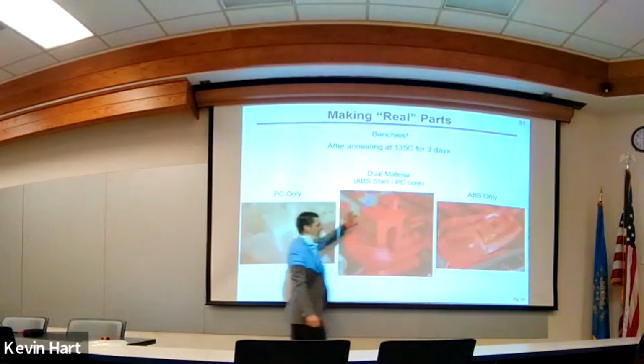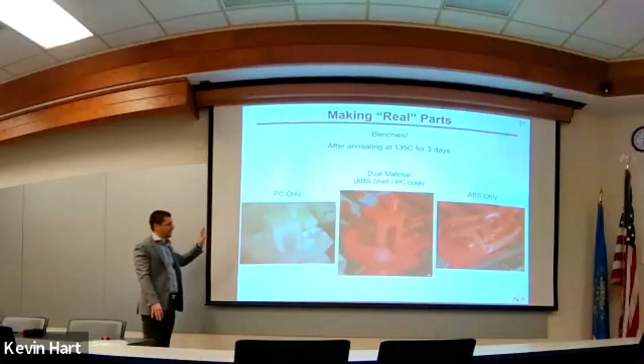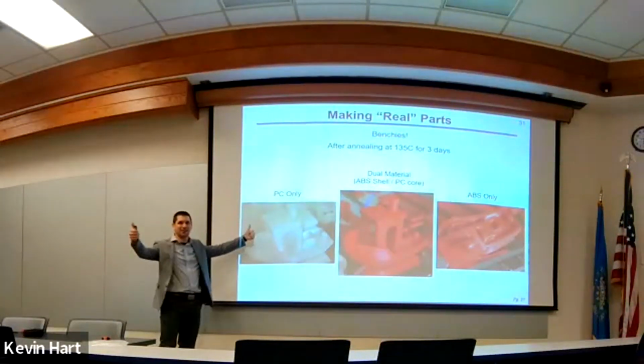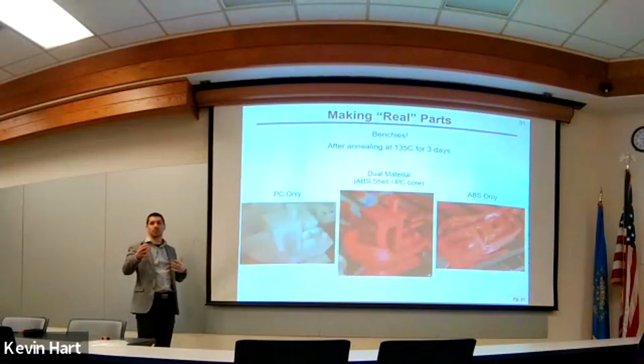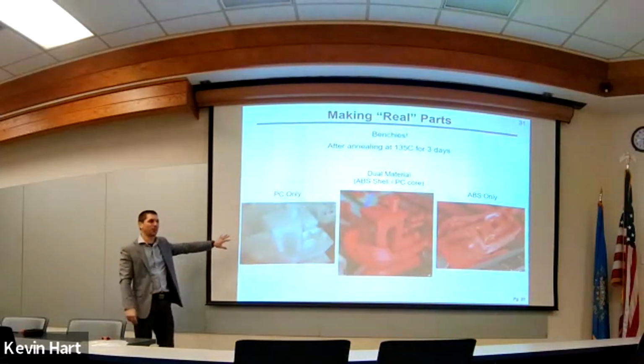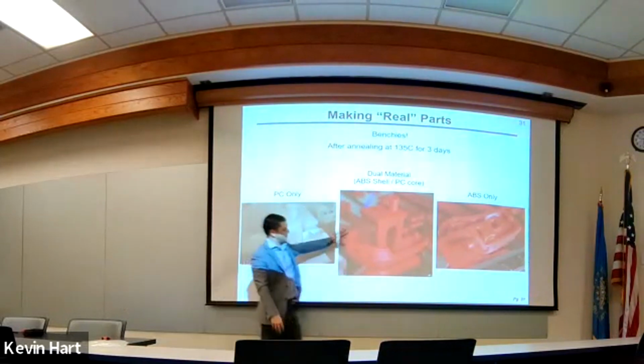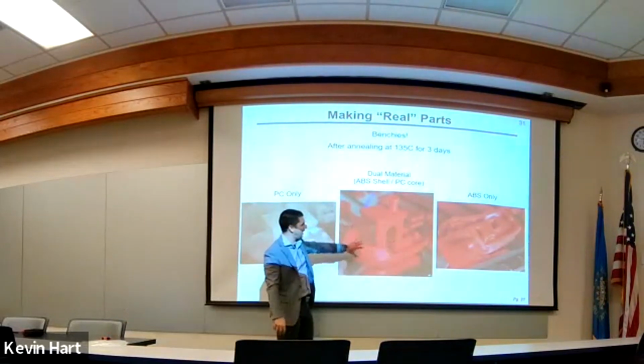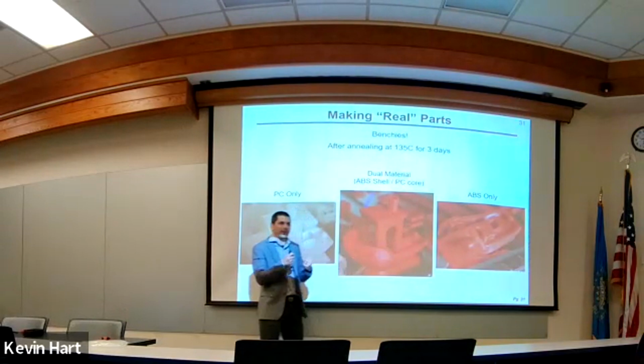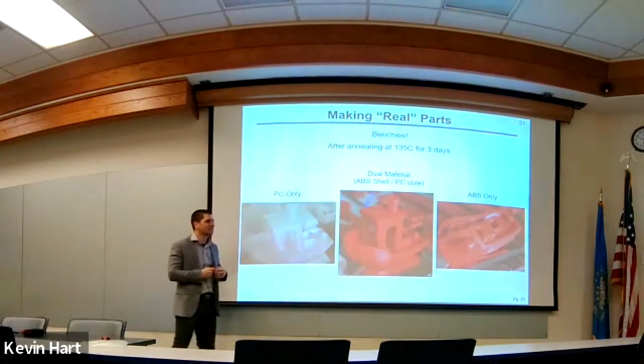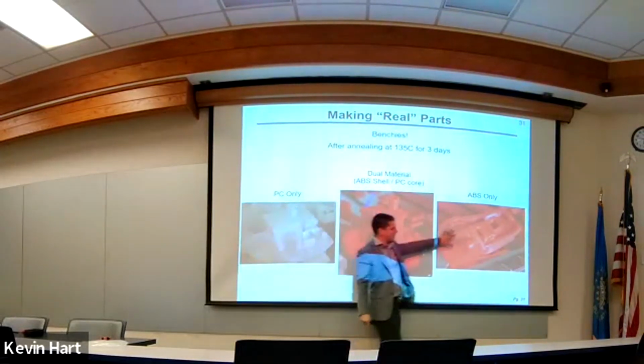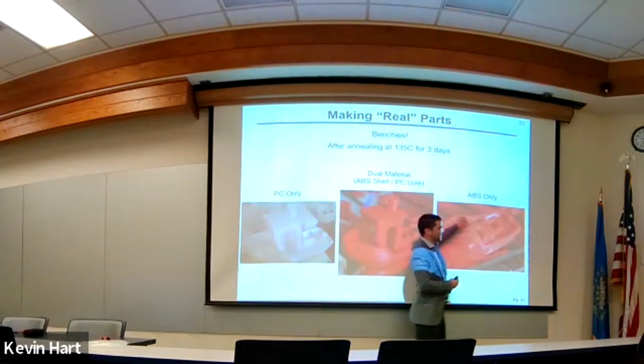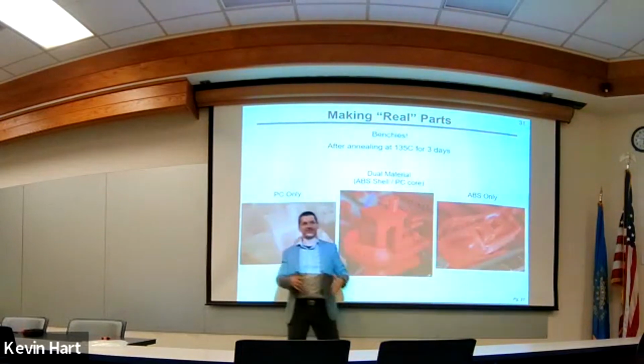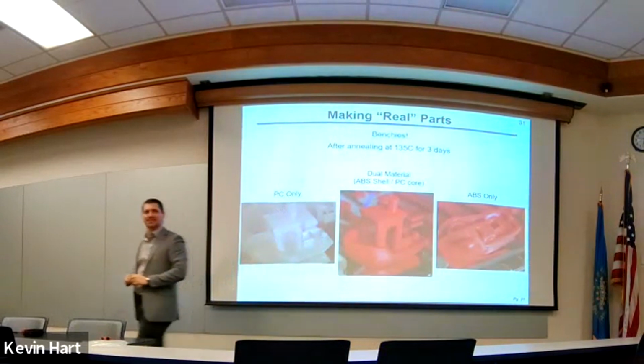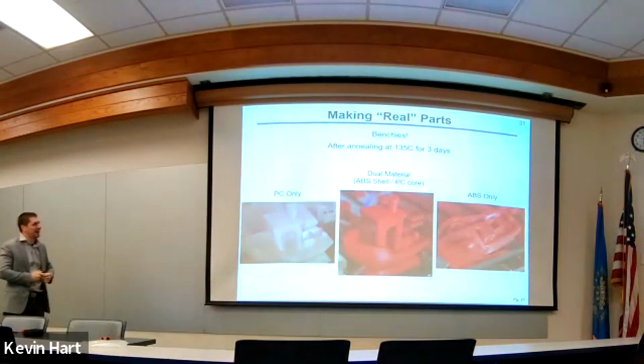We annealed all three of these at 135°C for 3 days. The polycarbonate survives because its glass transition temperature is 150°C, and we annealed this at 135°C. Our dual material filament printed benchy also survives because it has that polycarbonate skeleton inside of it. Okay? But the ABS, when you print it and it doesn't have that polycarbonate skeleton inside of it, you don't want to get on that boat. You know what I'm saying? All right. That guy didn't quite make the trip.